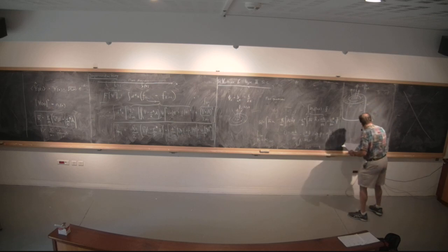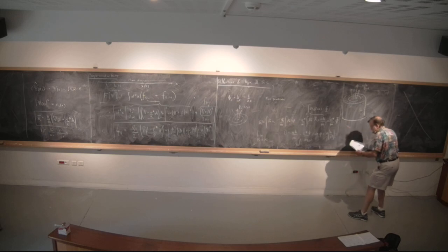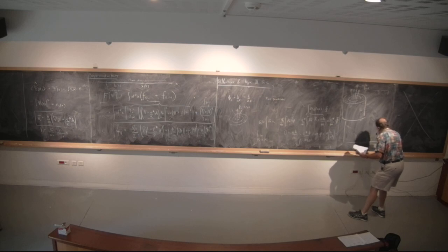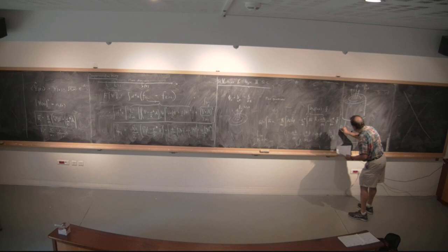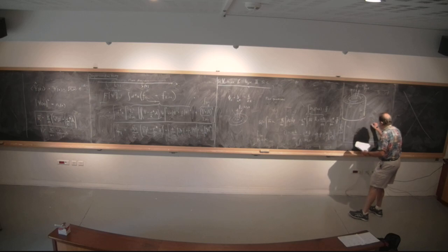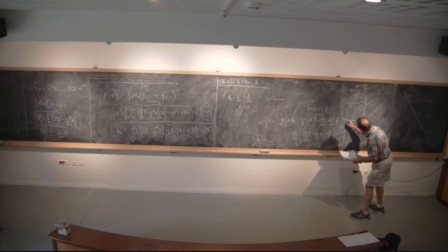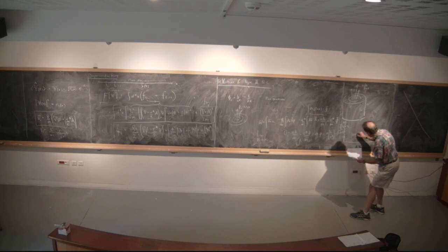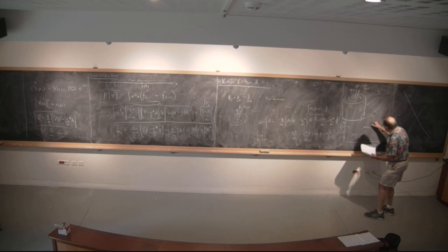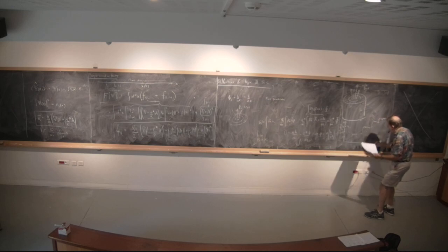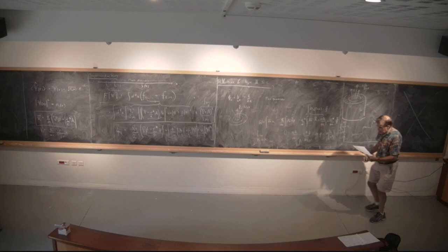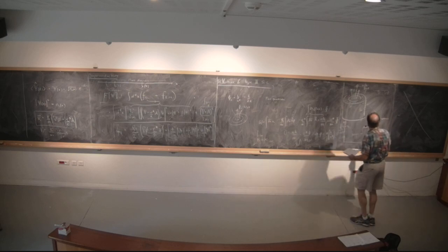And the way you can see that experimentally is you can actually measure the amount of flux running through it as a function of the external field. And here is the flux divided by h over 2e. And normally you'd expect it to go just a nice straight line like this, but it doesn't do that. In fact, what happens is that it quantizes. And so it just jumps. It stays 0 here. Then it jumps up, stays there. Then it jumps up again. Versus h here. And so this is the phenomenon of flux quantization.